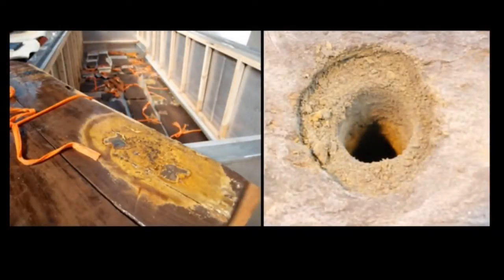Now, when we come to dry it, we have to be conscious of some other problems. Due to the wood being under the seabed for so long, it has foreign species lodged in it, such as sulfur and iron. The sulfur comes from the seawater, and the iron comes from, well, it's in the seawater, but also predominantly from corroded fixtures and artifacts that haven't survived that environment. Basically what can happen is you get these iron-sulfur compounds within the wood, and when they're exposed to oxygen, so when we're drying it, it can rapidly oxidize and form sulfate salts and sulfuric acid, which can be very damaging. This is kind of what they can look like on the artifacts. So they don't look very good, but also they're very acidic.